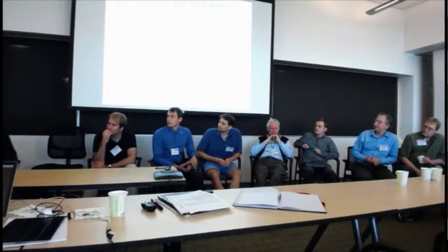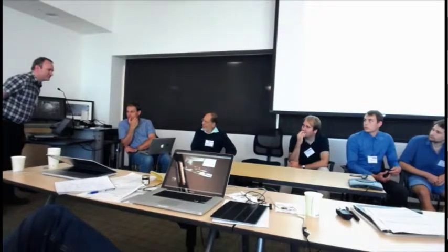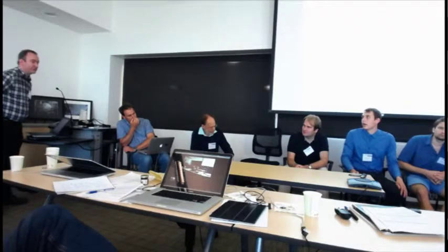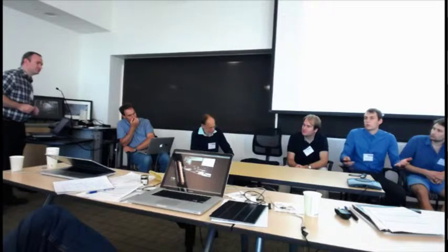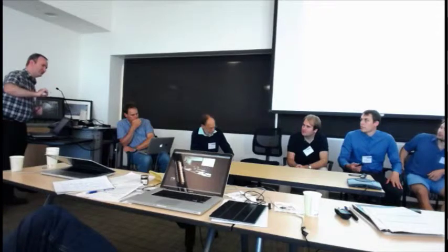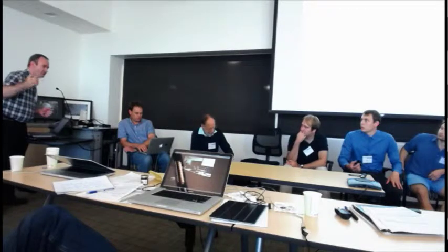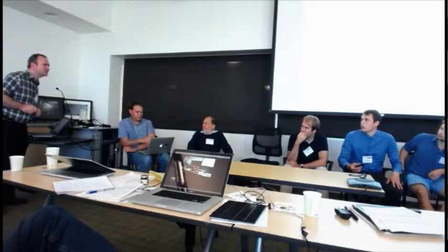Okay, you post-refine it, you calculate your partialities, but when you divide by your partialities, I guess we're cutting it at 0.2. But this is easy: you just have to divide your error by the same number as well. Yeah, so you end up with spots that have huge error bars, I guess. And if you treat the errors correctly, they will not contribute. Taking that to the next level, if you have big error bars, that means you need a lower weight. And the weight is basically the inverse square of the error bar, which means that averaging these things is equivalent to squaring the spot intensities first, or the fourth power. Is that right?